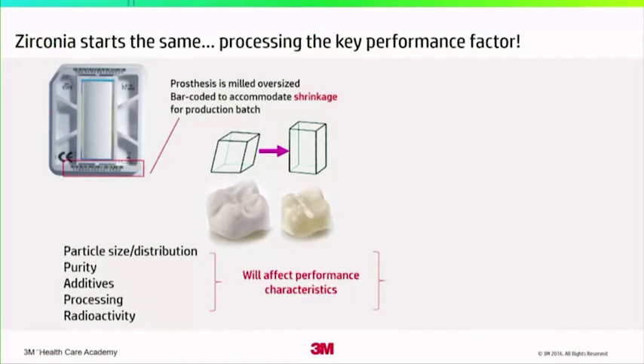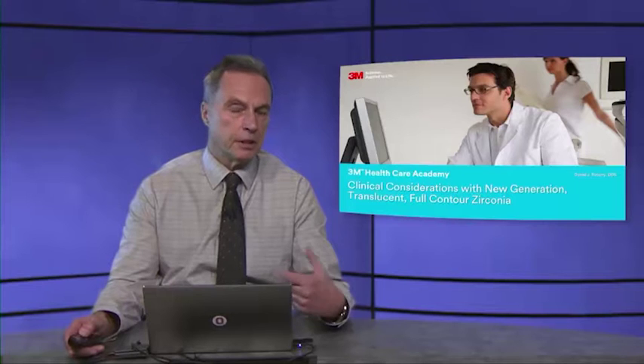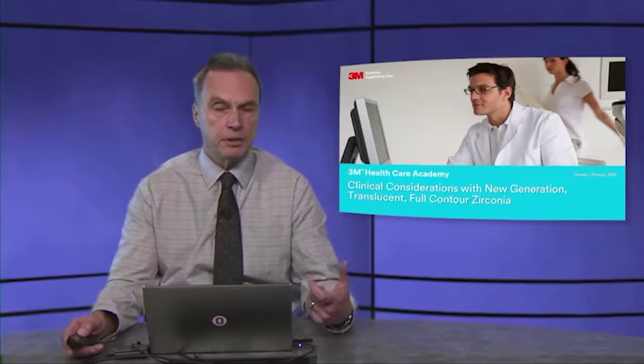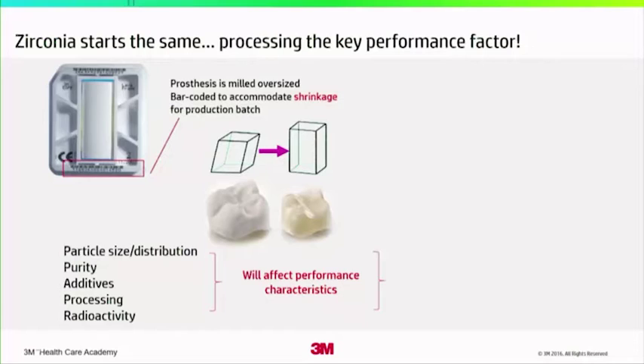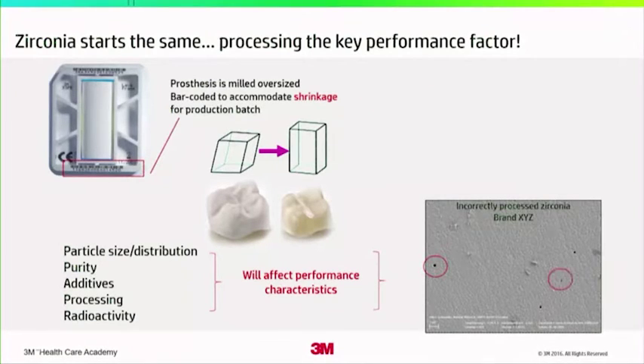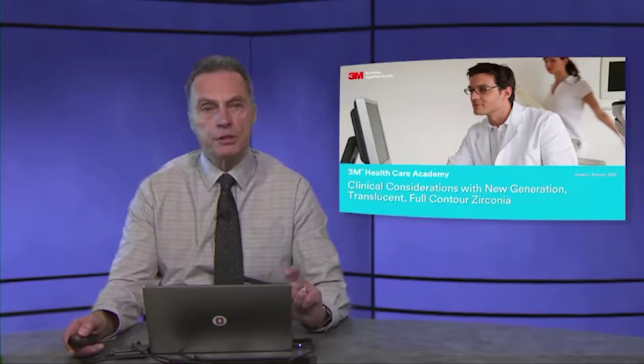By milling, I mean it's not ground, which is typically associated with diamond instruments, but rather it's milled with carbide burrs. And it's actually overmilled to compensate for the shrinkage that will occur, that is specific to each particular batch of zirconia. So simply stated, zirconia that's incorrectly processed, with impurities and a number of other flaws in it, can lead to poor performance. And unfortunately, a lot of doctors today are not familiar with where their zirconia is coming from or who is producing it.